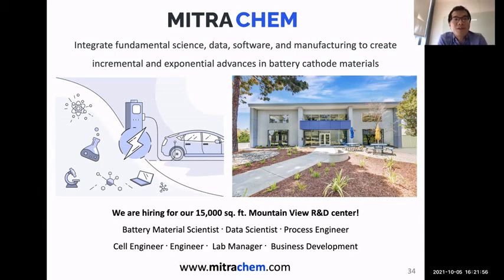So I think, Andrew, you just correctly characterized that the complexity of the problem is even more than I described here. And that's why an informatics-based approach is very much needed because, as Alp mentioned, you need calendar aging, cycle aging, you need temperature. There are so many things to consider. You have multiple chemistries. So this easily becomes a daunting problem. And my hypothesis, which is behind the founding of Mitra Chem, is that people become very risk averse. They don't want to change anything because it's kind of magic. We got it to this point and it works well, so let's not touch it unless it's broken. I think this approach will encourage people to explore more vigorously and look at options they haven't tried, because the cost of doing trials is now much lower, assisted by informatics.